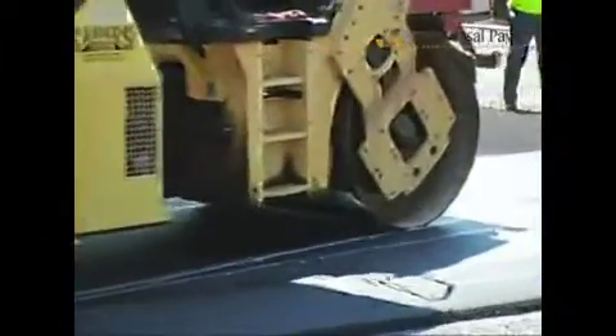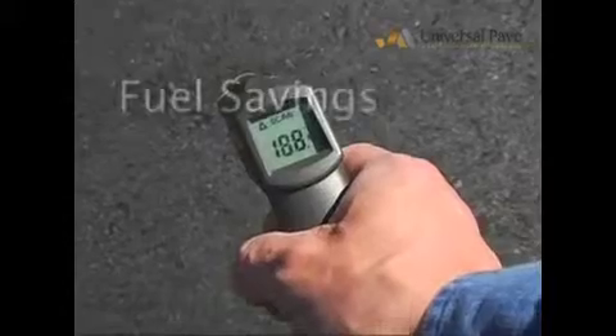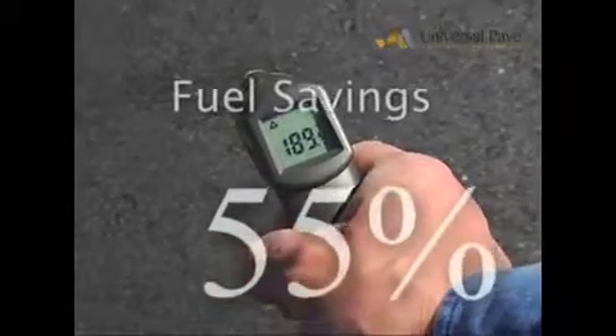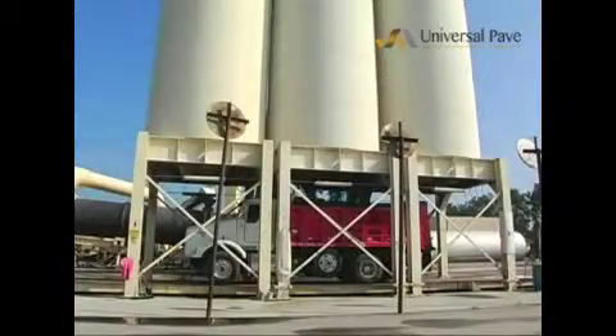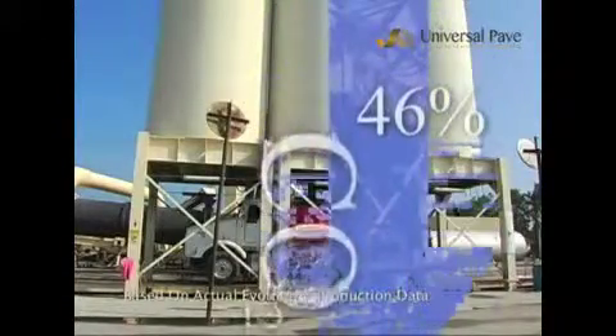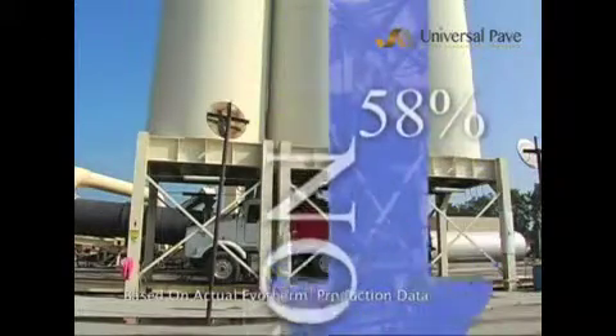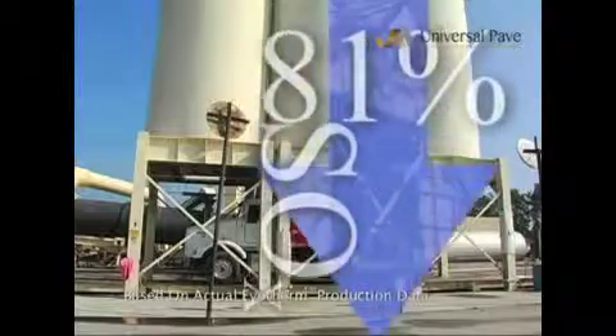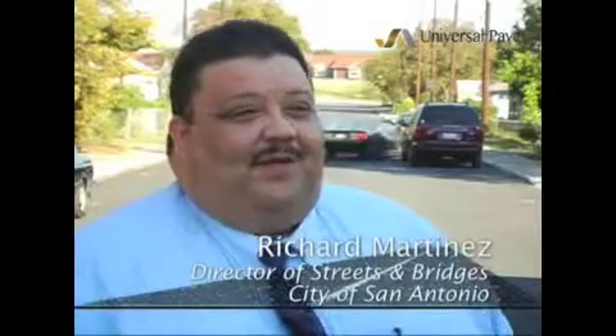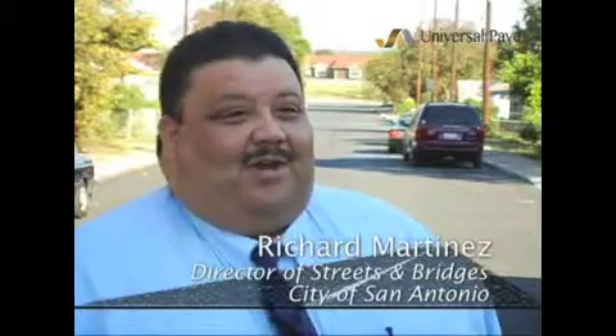Not only in the emissions and working conditions, but also in terms of the environmental benefits, in terms of saving fuel and energy, greenhouse gases. Most of these benefits are directly related to a significant decrease in the production and application temperature of the asphalt. Some chemistries offer a drop of 100 degrees Fahrenheit or more, and that translates into tremendous fuel savings, up to 55%. And with that, a dramatic decrease in emissions. Carbon dioxide down 46%, nitrogen oxides down 58%, and sulfur oxides down an amazing 81%. We're always looking for new and innovative ways to do things, and it comes down to dollars and cents.